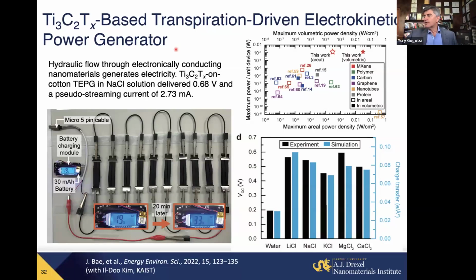You take a porous film, you dip it into, for example, seawater, water with salt, conducting, and as the water evaporates, there is potential development, and current starts flowing in a conducting substrate. People used carbon, but the amount of energy, power was very, very low. When we used MXene, because of its hydrophilicity, high conductivity, high concentration of electrons, we moved the areal and per device power by orders of magnitude. You can see this is a log-log scale, 2-3 orders of magnitude above everything done before. And now it becomes a practical solution.